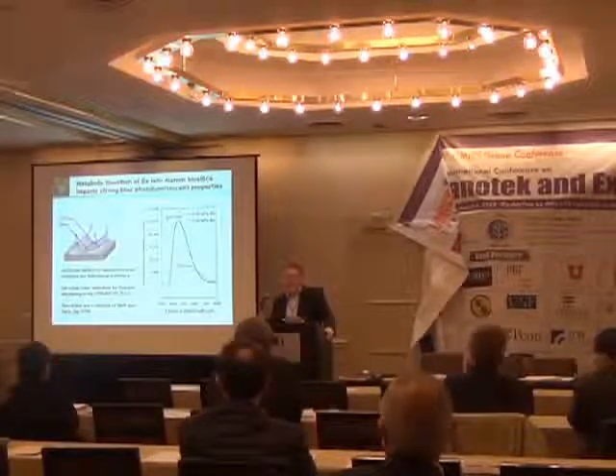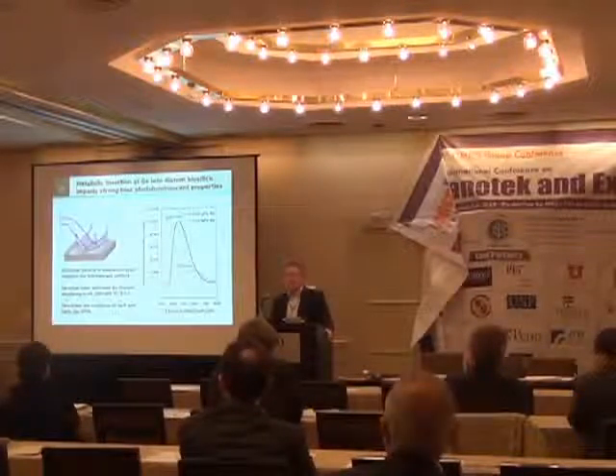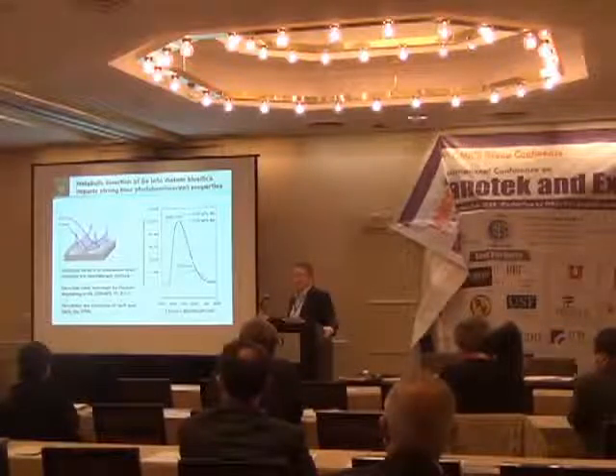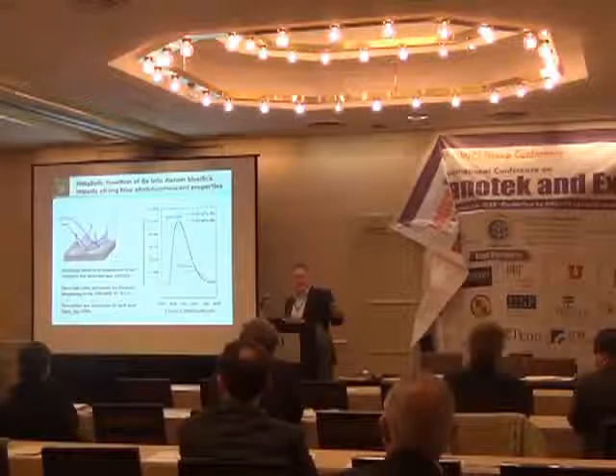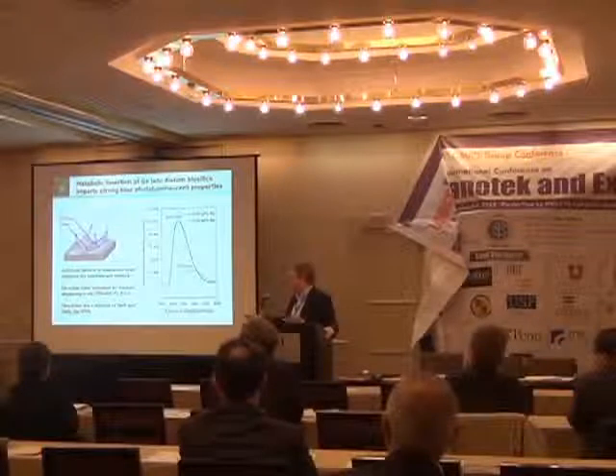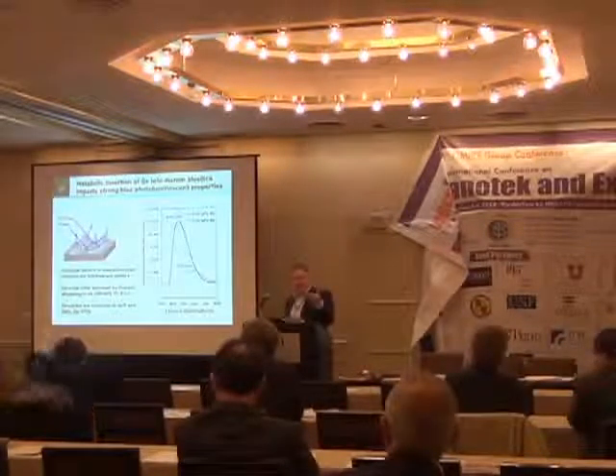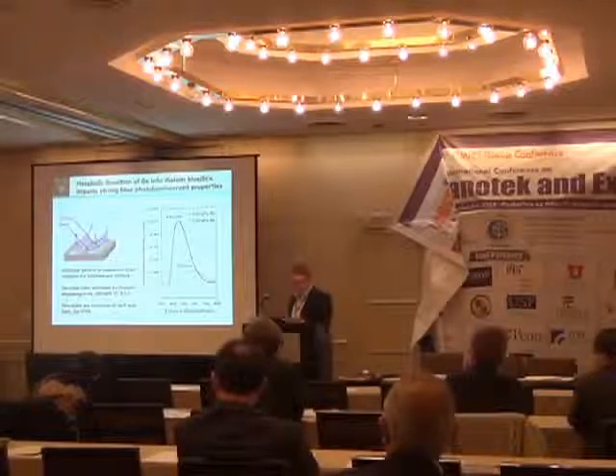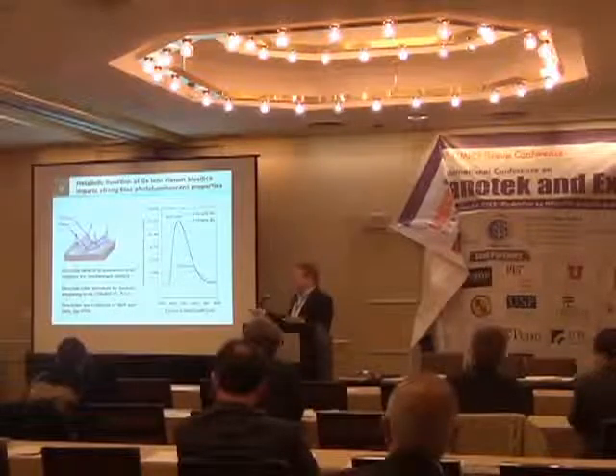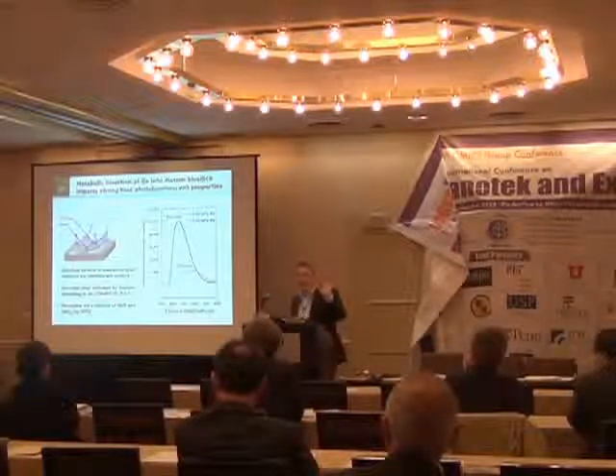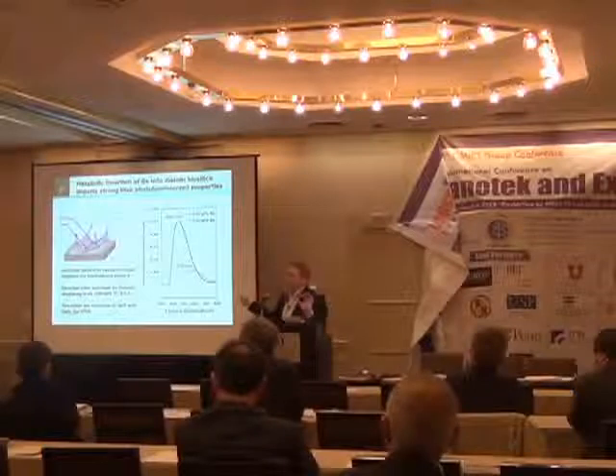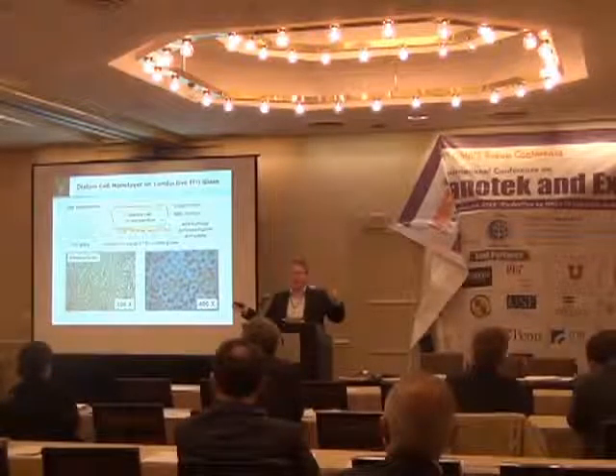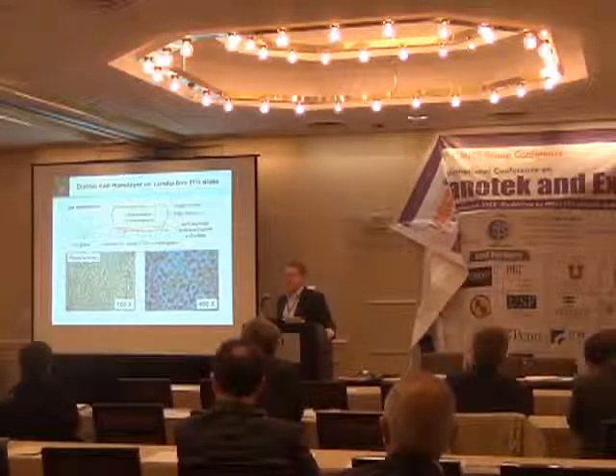What we found is that when we put this material into the diatom shell, we enabled a photoluminescent property. The native biosilica itself has some photoluminescence due to silanol groups inherent in the biogenic amorphous material. In our analysis, we used a 337 nanometer UV laser to excite the material and observed the emission. When we impart germanium oxide defects into the silica nanostructure, we greatly increase the photoluminescence emission capacity and also shift the center of luminescence into the blue range.